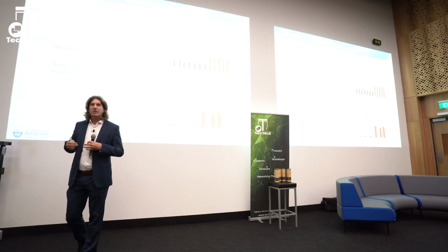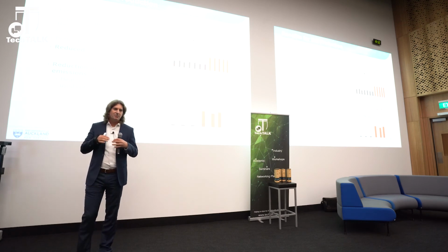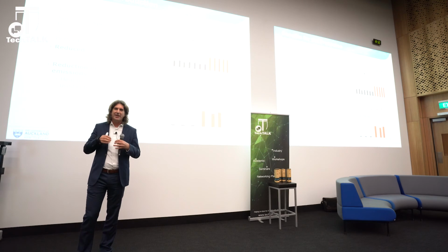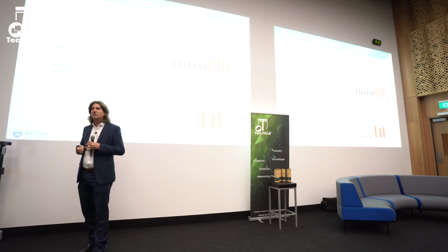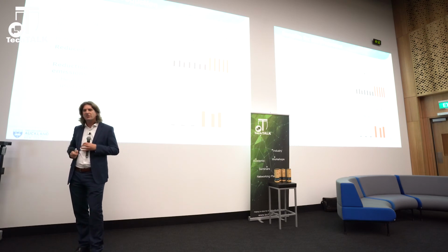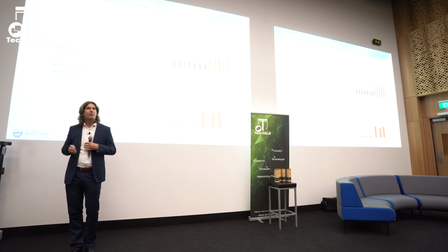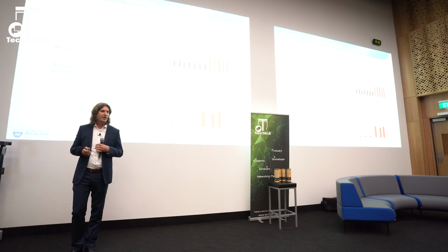Steel, which is 80 degree warm, is much smoother. They have some nasty steel grades which tend to break if they've got damages in the edges. And they've got in Parsytec a surface inspection system in the end, and detected, oh, we've got severe damages in the edges, and this strip didn't break. Meaning with every avoided strip break, you get 3 to 4 hours production time for free. And that is a kind of unexpected success of the process, which makes them quite happy.